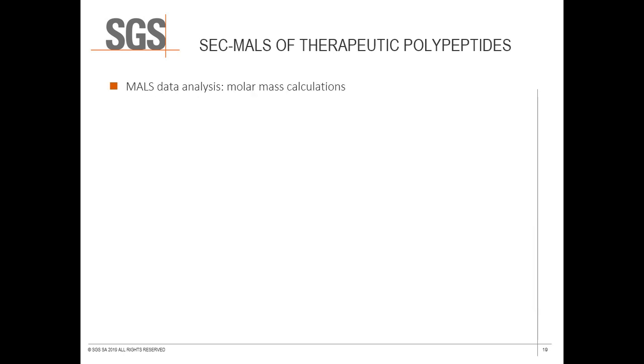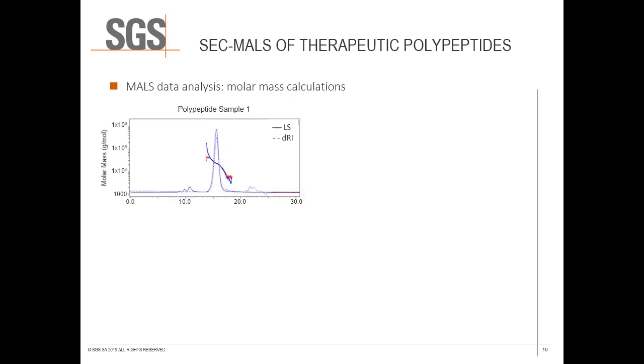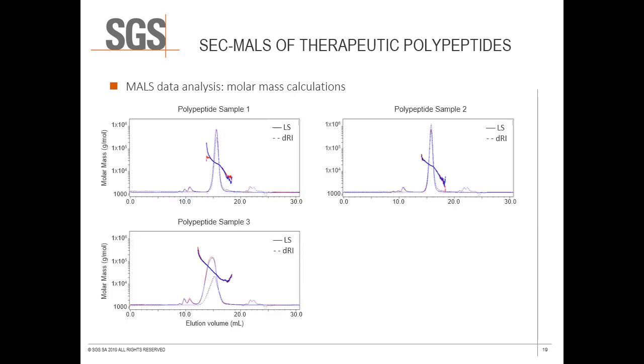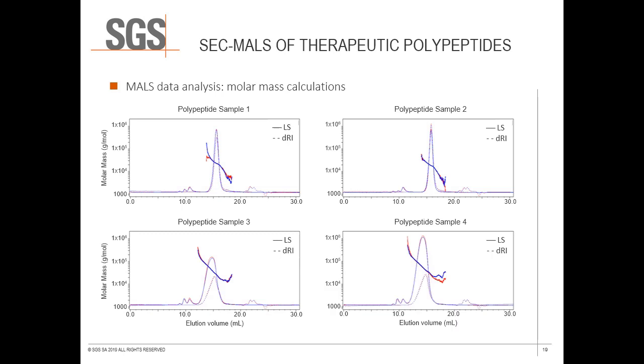The Astra software then relates the light scattering data from all detector angles and the concentration data provided by the refractive index signal to calculate molar mass values. The differential refractive index increment used here to relate the RI signal to concentration was determined by infusing various concentrations of the polymer sample into the refractive index detector and measuring the response as described previously.